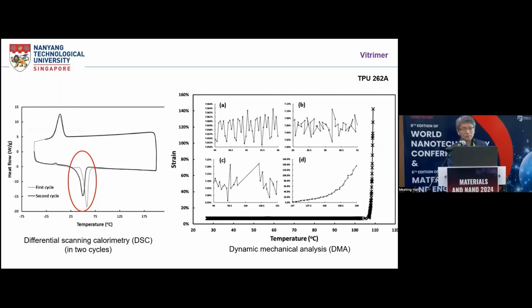So this is a dynamic mechanical analyzer, DMA, test, strain against temperature. We keep the strain almost constant, and we apply a cyclical loading. So within a temperature of about 40 to 50 degrees, you will see the strain response is rather periodical, which indicates the material is quite elastic. And if you heat up to 90 degrees, which is well above its melting temperature, as indicated over here, the material is still able to maintain the shape. As you can see, the strain is still about constant, although it's not so periodical as within this range.